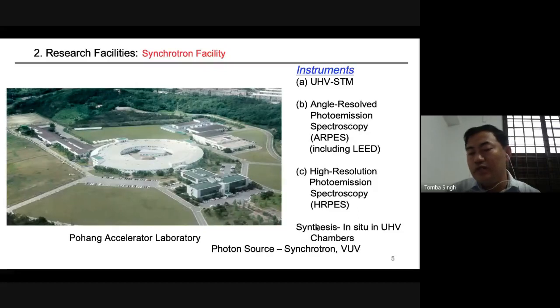We synthesize our samples in situ in ultra high vacuum, because in such systems cleanness and vacuum condition are very important. For layered materials, we can just peel them off and introduce them in the vacuum chamber. That means we peel the sample in the ultra high vacuum chamber, and without breaking the vacuum, we introduce it into the experimental section. For surface science, only the top few atomic layers on the surface matter. That's why it is very surface sensitive, and we have to have a very clean surface. So the environment inside the chamber should be ultra high vacuum. We use the photon source from the synchrotron, or if there is no synchrotron facility, then we use a lab source, a vacuum ultraviolet lab source.